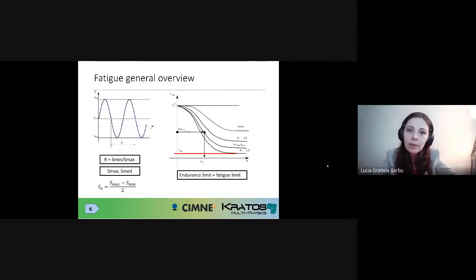Okay. Now, all of these cyclic loadings applied on specific components induce a change in the material properties. And these changes are recorded for a specific geometry by means of the stress-number-of-cycles Wöhler curves. What's important for me to explain to you is that there is no single stress-number-of-cycles curve. There is a whole family of Wöhler curves, where each specific stress ratio has associated a specific Wöhler curve. So we can somehow understand the concept of SN curves as a smooth surface, okay, which varies with the reversion factor.